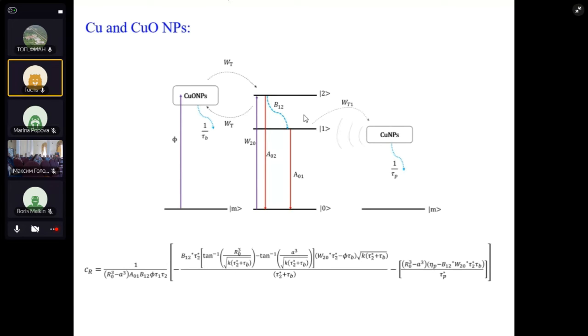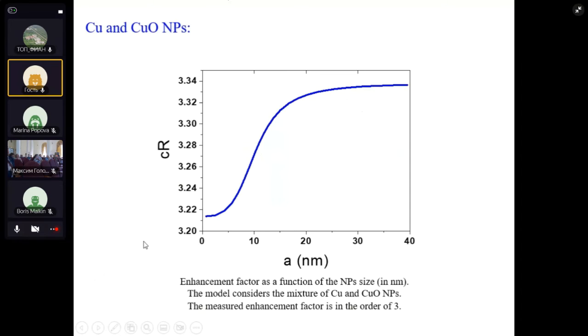But if we take into account both, and we know very well that copper is very easily oxidized, then we were able to set up an appropriate, more complex, system of rate equations, and we were able to estimate the enhancement factor in this case. And what we see is that there is good agreement. We were able to plot the enhancement factor as a function of the particle size.